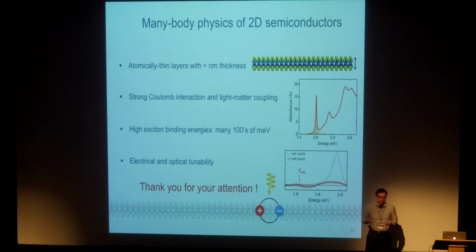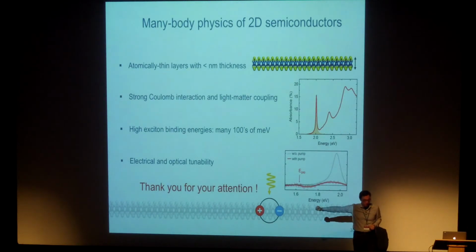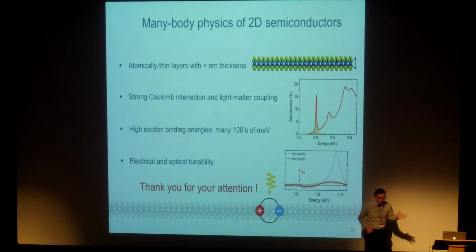So the two electrons are not hybridized in a trion. And what happens when they optically recombine: the excitonic core, so to speak, the electron hops into a hole and emits a photon. The momentum is transferred partially to the remaining electron. And that actually even relaxes the selection rules for the recombination of the trions.